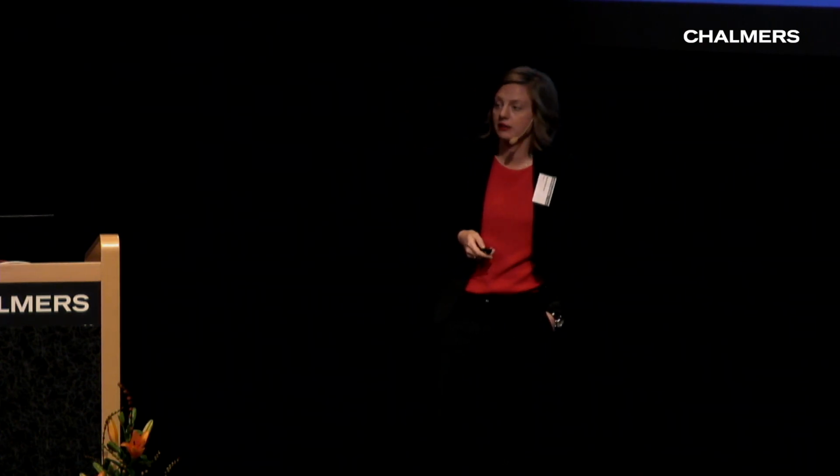Some more material properties that I presented. Our processes apply to the F75 standard, and need a HIP process, but no other or further heat treatment. And also for osseointegration, it can actually show to have a similar behavior as titanium in the study we showed.